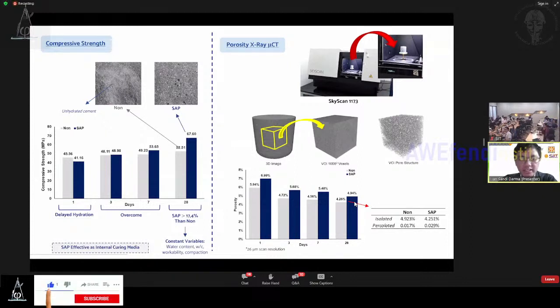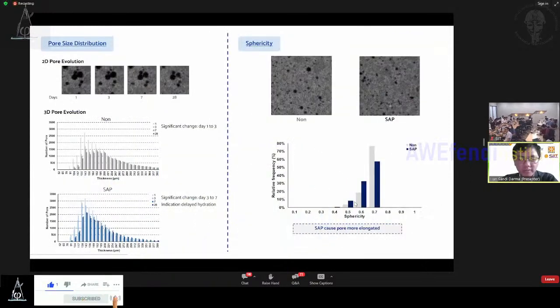Additionally, this study uncovered the phenomenon of delayed hydration from day 1 to day 3, as evident in the compressive strength between days 1 and 3, which has yet to be explored in previous studies. Porosity of the specimen can be obtained from X-ray microscopy from a 3D image. A volume of interest of 1000 voxels was chosen on the core structure and obtained through thresholding. Porosity of SAP at 28 days is slightly higher, but the pores are mostly isolated, so the superabsorbent polymer can be assumed not to have significantly influenced it. Through two-dimensional pore evolution, we can tell that pores become isolated over time.